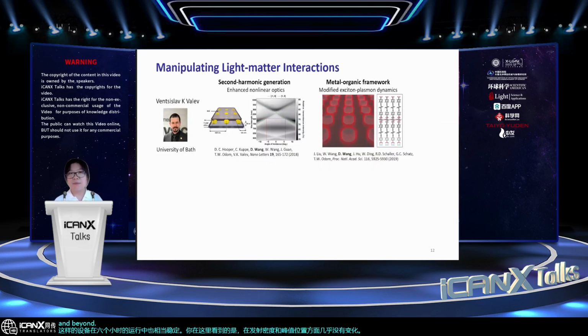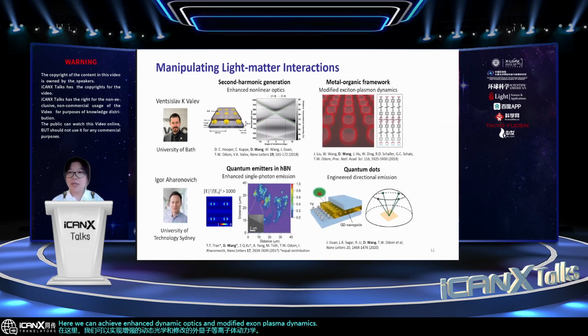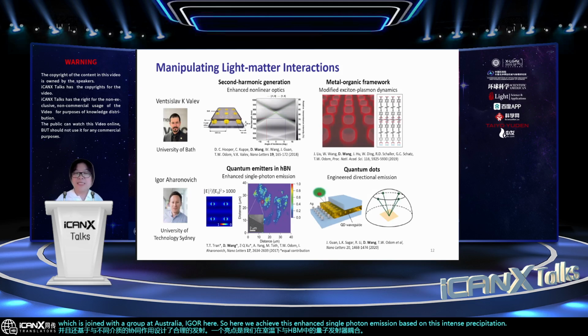And beyond the upconversion particles, our system also has the freedom to interact with different types of gain mediums and for different elemental interaction processes. Here we can achieve enhanced nonlinear optics and modified exciton-plasmon dynamics, and also engineer the directional lasing emission based on the synergy with different gain mediums. One highlight is our coupling to the quantum emitters in hBN at room temperature, which is a collaboration with a group in Australia. Here we achieve enhanced single photon emission based on intense Purcell enhancement and localize these quantum emitters in hBN to our hotspot regions.